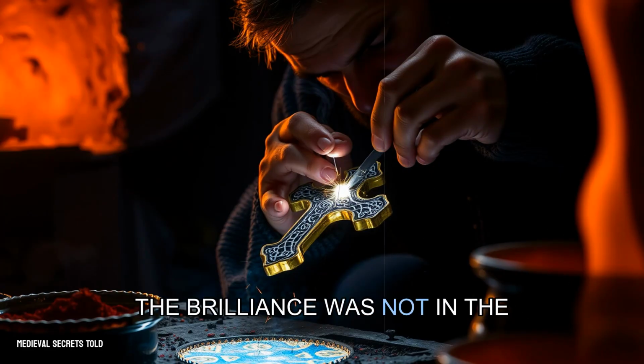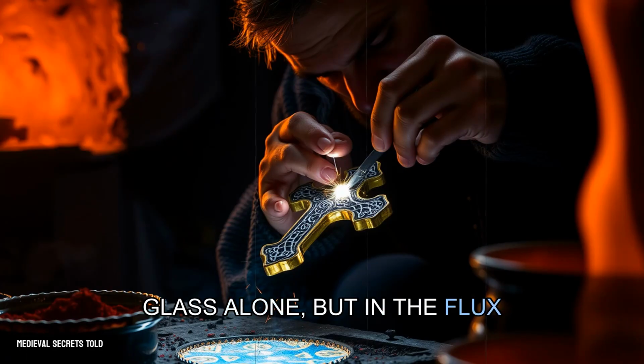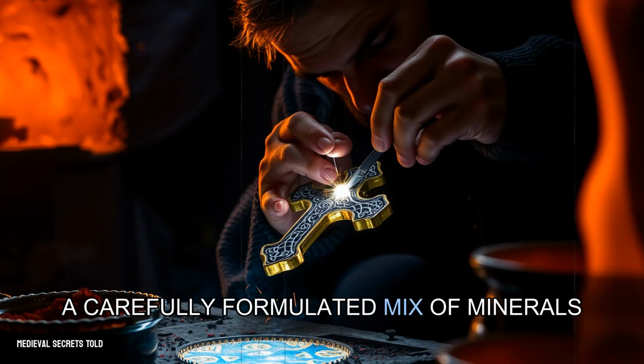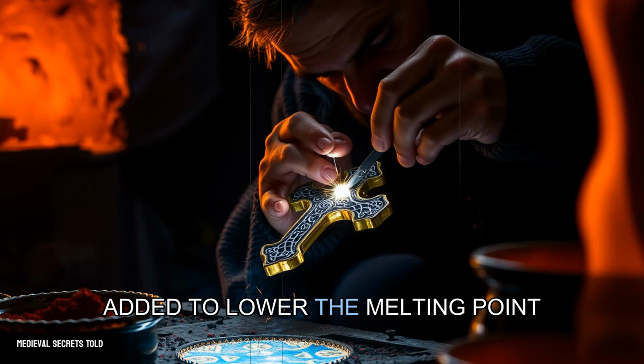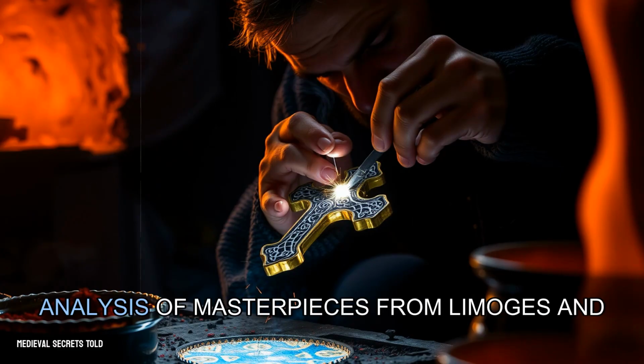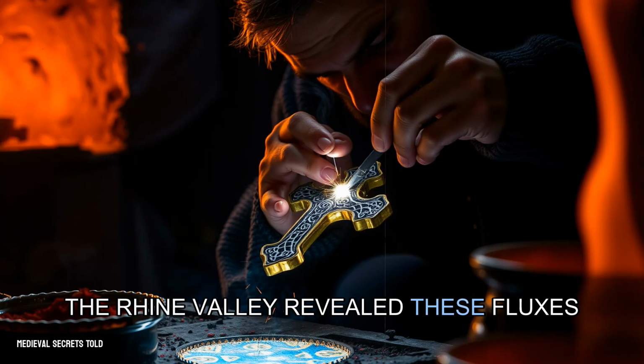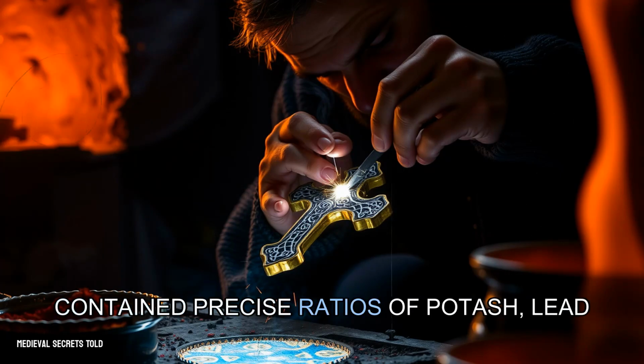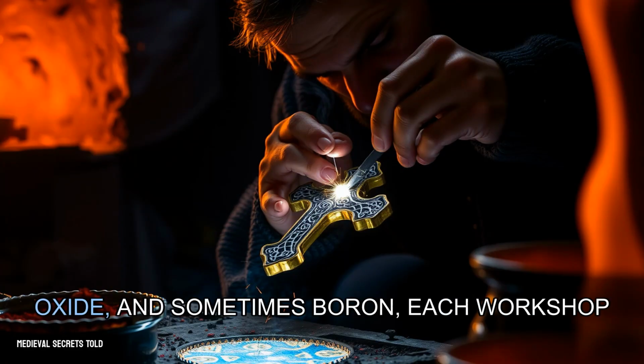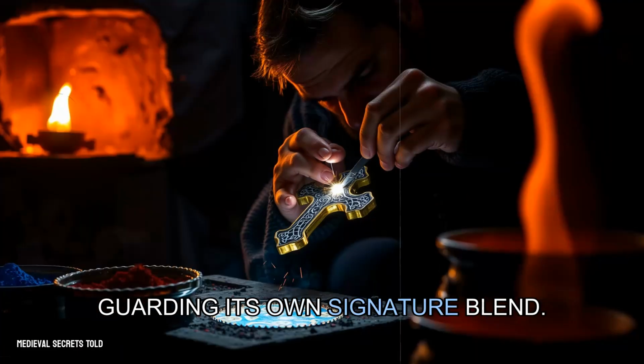The brilliance was not in the glass alone, but in the flux, a carefully formulated mix of minerals added to lower the melting point of the silica. Analysis of masterpieces from Limoges and the Rhine Valley revealed these fluxes contained precise ratios of potash, lead oxide, and sometimes boron, each workshop guarding its own signature blend.